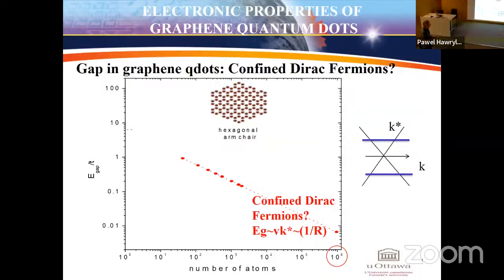Now, this dependence of the band gap on the number of atoms can be understood in terms of confined Dirac fermions. So I have my Dirac fermion cone, and size imposes some lowest possible allowed wave vector, K star, and 2 times K star is the band gap, and this is proportional to 1 over R, the radius of my quantum dot, and that dependence on number of atoms is exactly that. So in a sense, when we look at this band gap, we are confining Dirac fermions to a different size quantum dot.